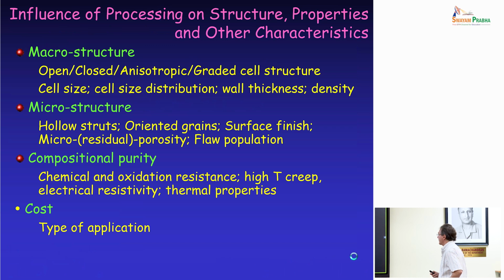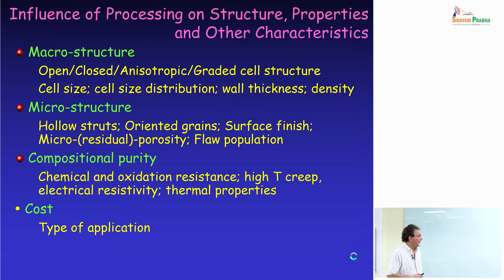So let me first mention the influence of processing on structure and properties and other characteristics. From the macro structure level point of view, you can obtain open, closed, anisotropic, graded cell structures. You have a certain cell size, a certain cell size distribution, a certain wall thickness, and of course, a certain amount of porosity. So you can control all these parameters. In terms of the microstructure, you can have hollow struts, so the solid component can be hollow.